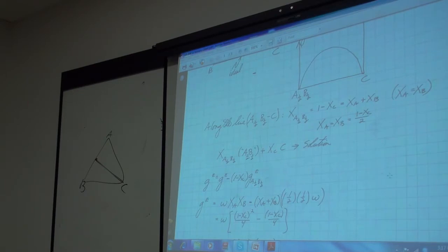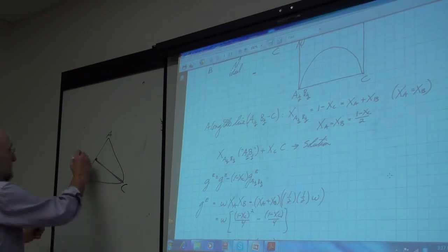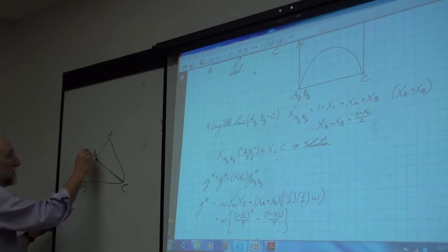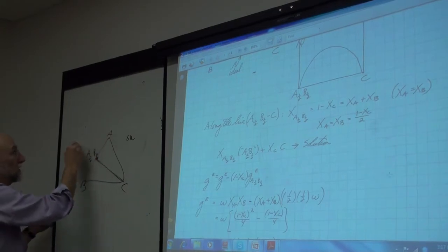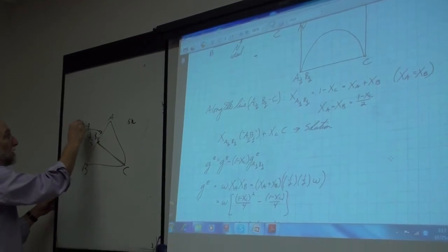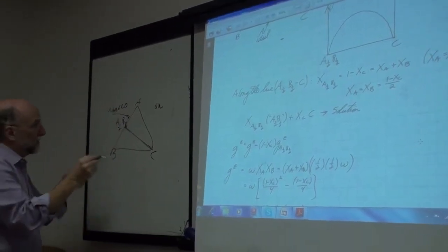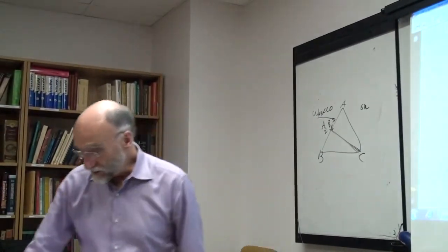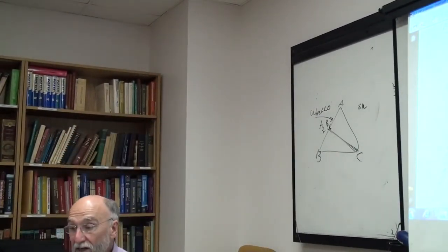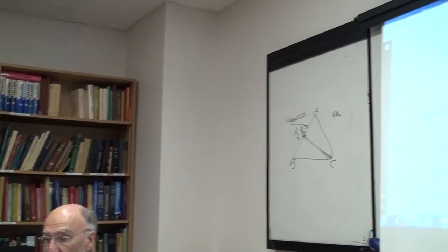As I said, as you add C, here you have your complexes AB. Here you have an A1/2, B1/2. You have not complexes because you're using the Bragg-Williams model, but you have a very negative omega AB along here. So you add C, you're breaking up the AB pairs. That's why you get the positive deviations, but let's actually do the mathematics.